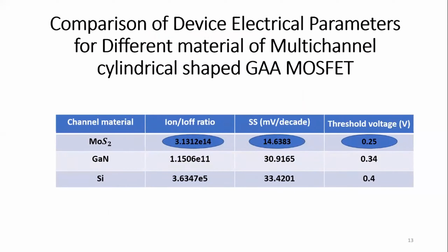Now, here are the results for cylindrical shape device electrical parameters for gate-all-around MOSFET, for molybdenum disulfide as TMD material, gallium nitride, and silicon. MoS2 multi-channel shaped gate-all-around MOSFET has better device electrical parameters than gallium nitride and silicon as channel material. We can see here it provides more Ion/Ioff ratio than gallium nitride and silicon as channel material. When molybdenum disulfide is used as channel material, it shows 52.65% and 56.19% decrease in subthreshold swing than gallium nitride and silicon respectively, as well as 26.47% and 37.5% decrease in threshold voltage.